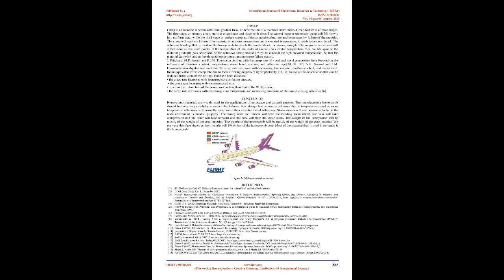The analysis also focused on their behavior in the orthotropic or off-axis directions. The model that was made makes it possible to correctly predict the stiffnesses and the critical buckling load, which is considered here, as in previous publications, as the sizing load. Gornat et al. 21 analyzed nonlinear shear behavior using the asymmetrical shear test but proposed a nonlinear model based on damage mechanics only in compression. The stress portions are shown in the figure below.